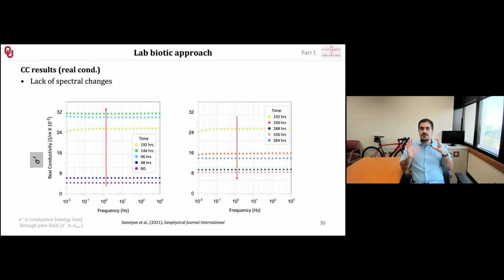Taking out the real conductivity just to show you that the complex, the imaginary part is sensitive to the pore size distribution, surface area, grain size, and so on. The real conductivity is only a measure of solution conductivity and porosity. We can clearly see that there are no such peaks to tell us about the grain sizes or pore sizes in the electrical conduction that is happening through the pore filling fluids at all. So we certainly need to use the complex conductivity methods or the induced polarization technique if we are trying to monitor soil sterilization in the field in the future.